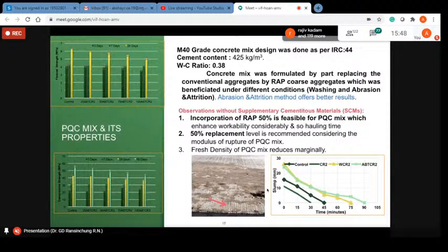Now these are the graphic bar charts prepared from the findings of the laboratory studies. For the different percentage replacement levels, 25%, 50%, 75%, 100%, we have tried. In this slide, our study is confined to only the abrasion attrition methods. We are not talking about the other beneficiation methods. Through this, if this method is employed, then incorporation of 50% RAP is feasible for the PQC mix. Because the mixing of these RAP materials enhances the workability considerably, and the hauling time of the concrete mix is considerably extended.